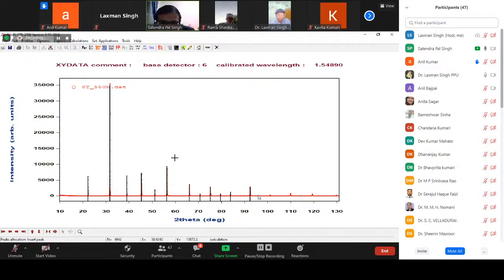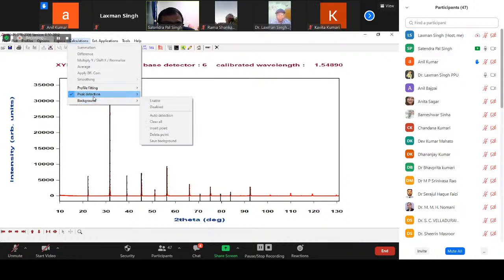For indexing, if it is a complex unknown system, we require at least 20 peaks. But this is a simple cubic system, so there are not enough peaks. Even if you go up to the high 2 theta, 1, 2, 3, 4, 5, 6, 7, 8, 9, 10, 11, 12, 12 peaks are present. Now, the next procedure, we have to save this peak. So let us save this peak.